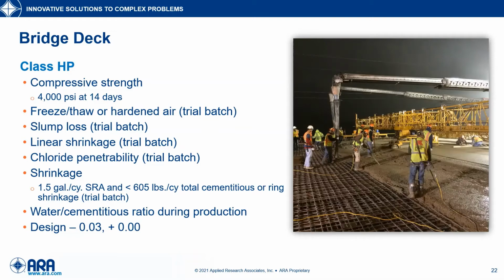And so, with the bridge deck mix and the Class HP, we're really focused on mitigating shrinkage cracking because it's used for bridge decks. And that's usually achieved, the shrinkage mitigation, through either optimized proportioning and shrinkage reducing admixtures or lightweight fine aggregate for internal curing.